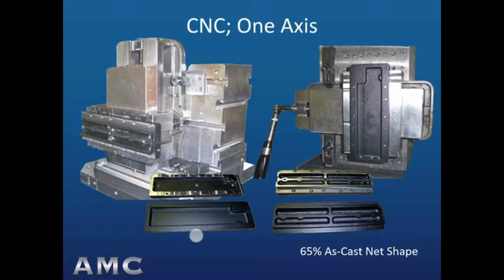In this case, the draft offset is the same all the way around the casting, so a 3 degree dovetail on the fixture's clamp surface can readily be matched to the draft. The important part of fixture design against a draft surface is to clamp the casting at the same offset level wherever the casting's draft is touched.